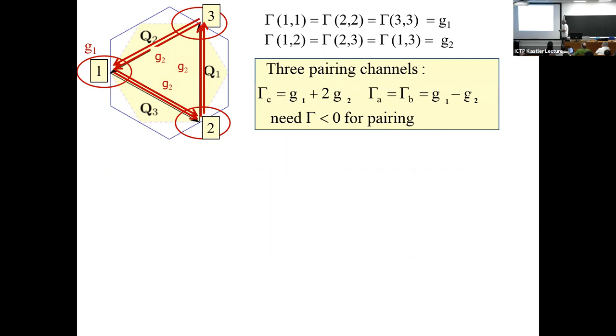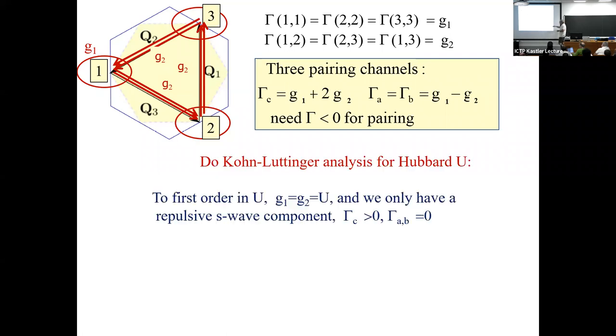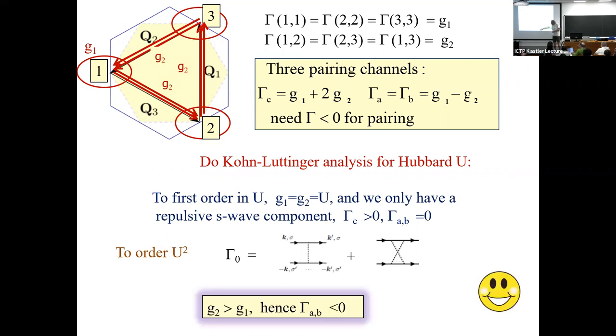When you solve this equation, you get, of course, one channel that is S wave, no question about this. It's repulsive and will stay repulsive forever. But there are two other degenerate channels for which the interaction is the difference between these two couplings. The story is the same as before. We start with zero. If we start with Hubbard interaction, we need to go to second order to see what happens. And predictably, this guy becomes negative. And you get more repulsion at large momentum transfer than at small momentum transfer.